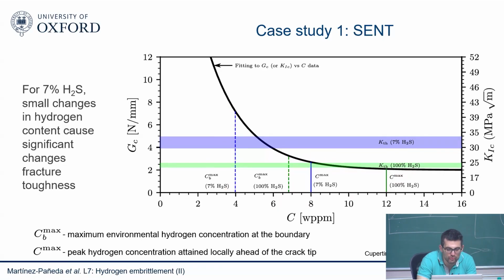But those small changes in hydrogen concentration will bring very little change in toughness in the 100% H2S, because we are close to the plateau, which means that those small changes are not going to change very much the result of my experiment. That's why I see the repeatability in the experiment.